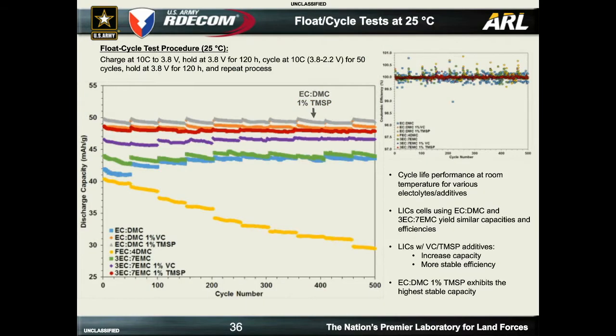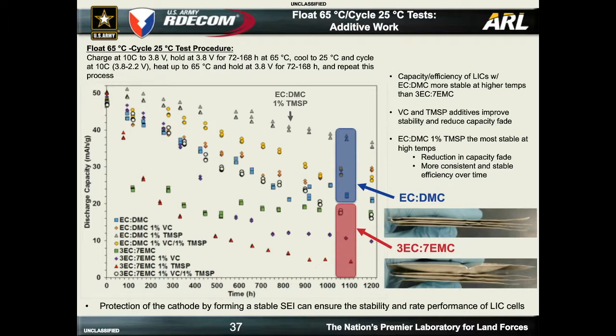Here we're doing float testing, so the standard test for LICs is to hold the voltage at the upper charge voltage. In this case, it's 3.8 volts for 120 hours, and then do some cycling, and then repeat that process multiple times. And here, this just shows with the additive TMSP, we get some better performance. Here we're floating at 65C and then cycling at 25C, and again, you can see some benefit from additives here, TMSP.